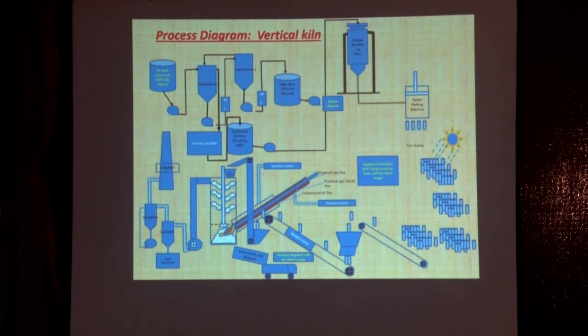It is not dropping unless they reduce fuel consumption, because everybody is concerned about optimizing fuel consumption. So one thing is clear: if we have to reduce the fuel consumption, we must have lesser moisture in the lime mud. And sometimes nature provides renewable sources to get it dry without any cost. So our plan is why not go for the vertical lime kiln. But in a vertical lime kiln, we cannot directly feed the lime sludge. You have to compress the sludge into pellets, because flue gas must pass through these materials. Even this vertical system can be integrated with the rotary lime kiln.